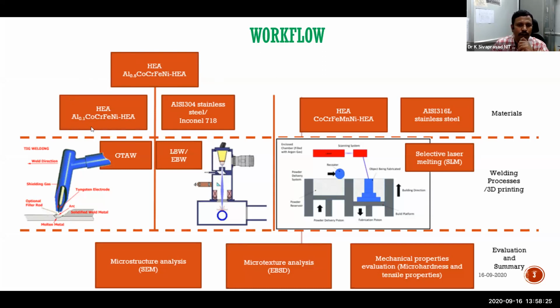Then we moved to aluminum 0.1, which is single phase FCC, relatively highly ductile, with much higher work hardening ability than 304 and Inconel 718. Why we have taken this combination is that all are FCC, FCC, FCC. It is supposed to be weldable according to mechanical engineering concept, but according to metallurgical concept, there will be a huge alloying system. When you are welding, they will melt down and diffuse inside, and there is a lot of probability that they will form undesirable phases and brittle phases. So there is a huge problem associated with joining of 304 and Inconel 718.